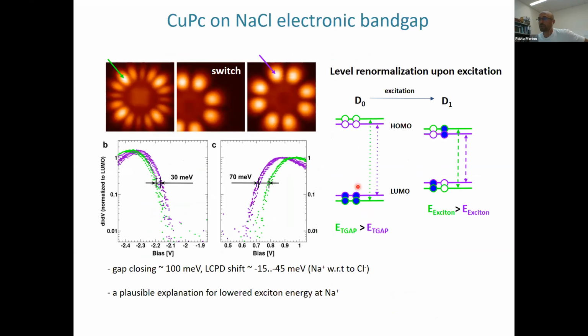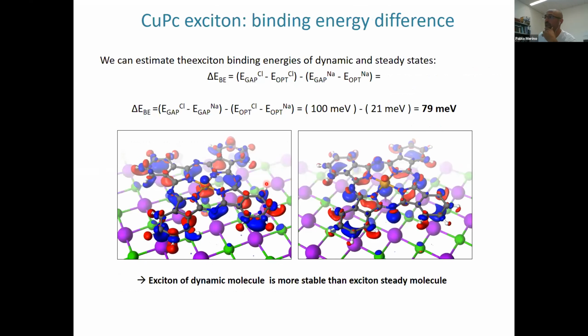And what we found out is that in this case, we are having a change in the electronic gap of 100 milli-electron volts, which is much bigger than the 20 milli-electron volts that we saw on the optical spectrum. So this is an indication that we're having a change in the exciton binding energy between the 2 states of the molecule. And actually, we can calculate the change in the exciton binding energy between the dynamic and steady states, because we measure the difference in the electronic gaps and the difference in the optical gaps.